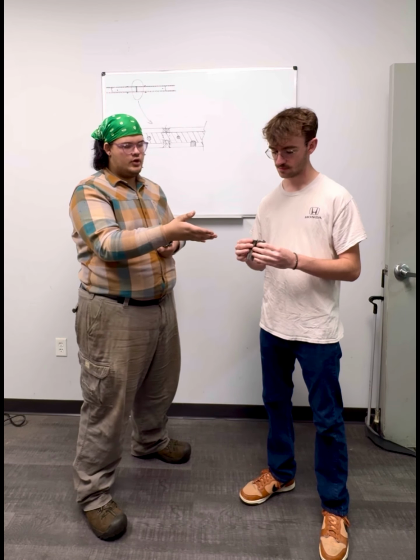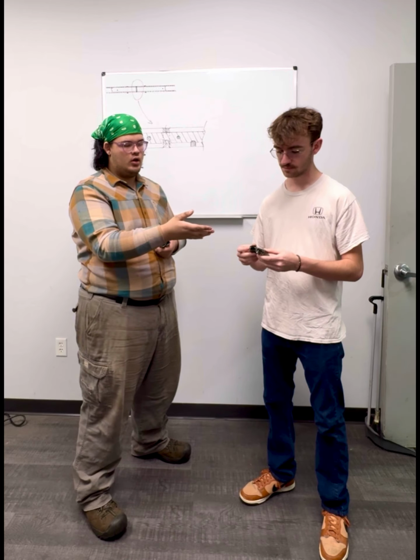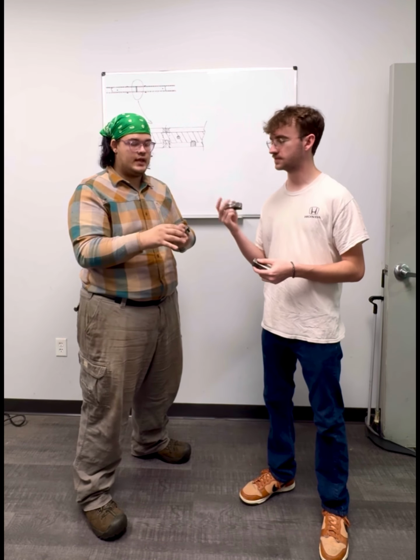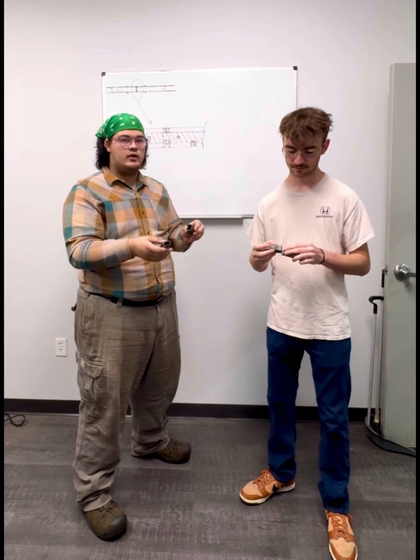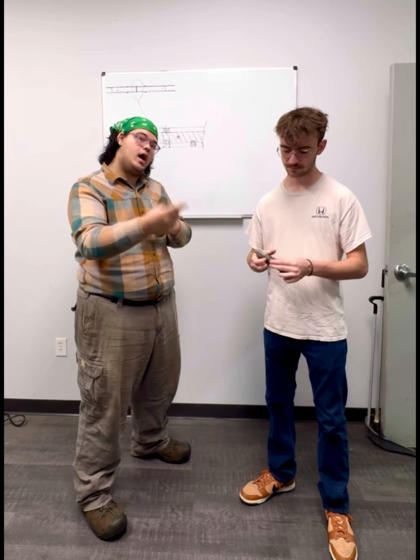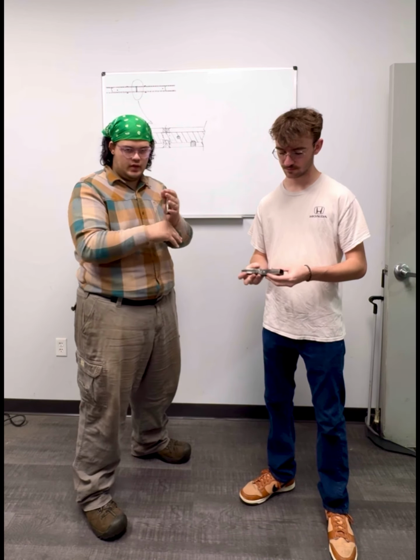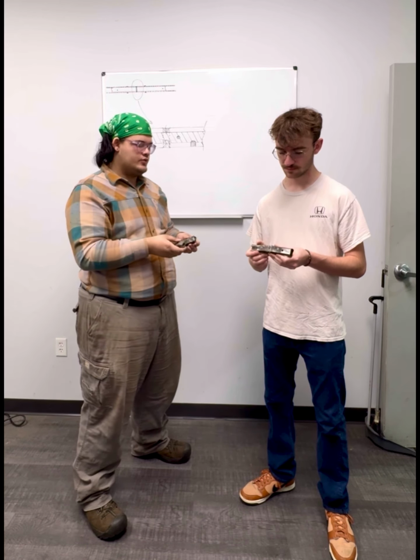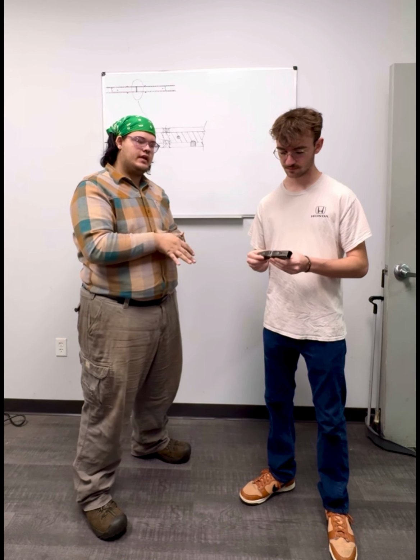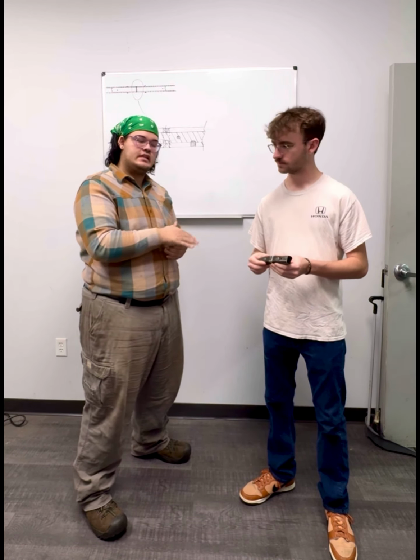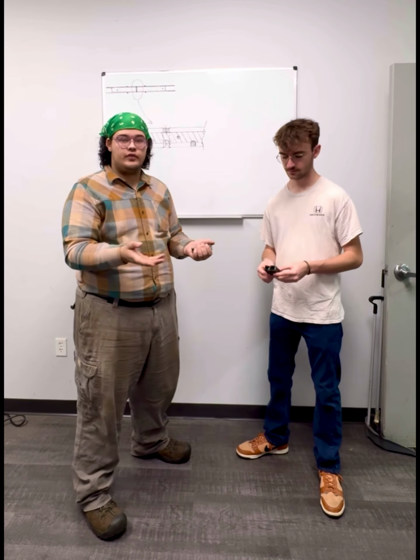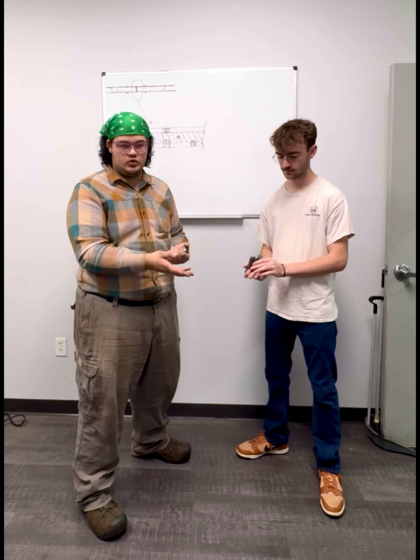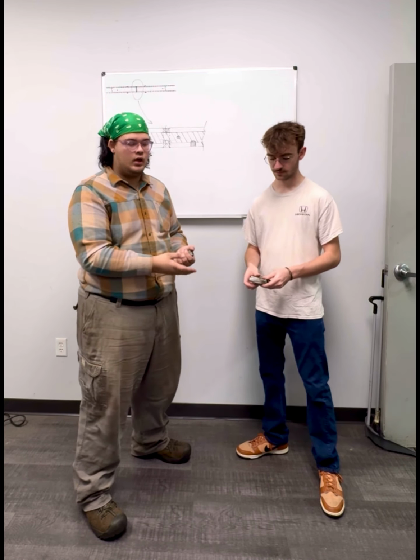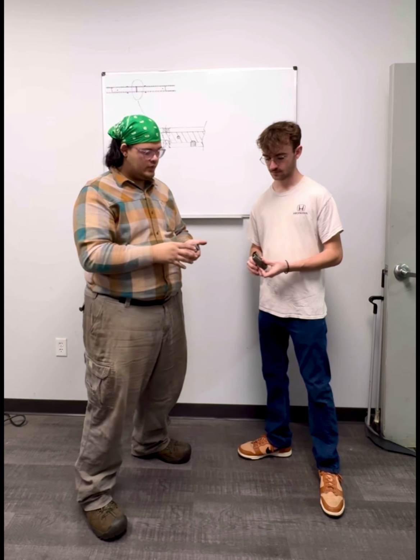This no penetration piece, however, only held up to 2 bends. These were bent roughly 15 to 30 degrees in opposite directions until the joint had completely failed. So we were attempting to simulate fatigue to a certain extent. Obviously, we didn't have the best equipment to do so, but you get an idea of where cracks will start to form with fatigue based off of just where the weakest parts of the joint are in general. So while we shouldn't conflate the two, there are a lot of similarities that we should pay attention to.